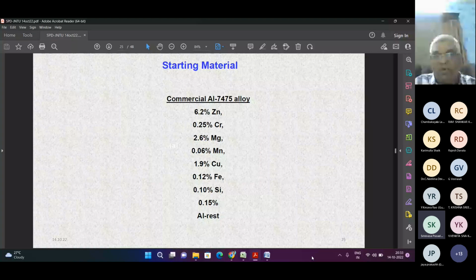The 7 is for the series of zinc magnesium alloys, 7475. This is a high strength aluminum. If you look at the 1000 to 8000 series, the highest strength you get is for aluminum zinc magnesium alloys only. Since it contains some zinc, you get some corrosion problem in this one, and this material is extensively used.